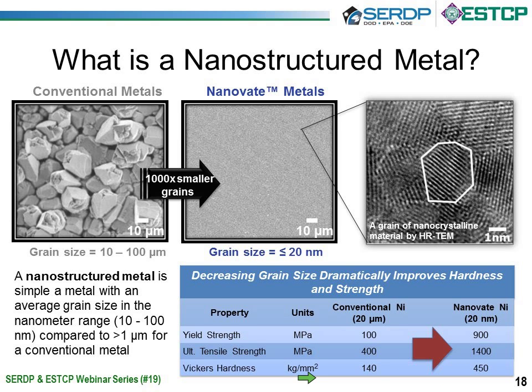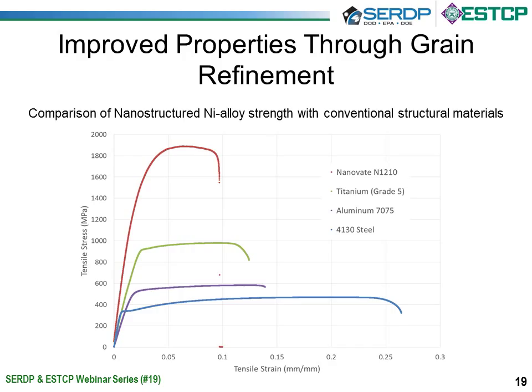On the next slide, it shows an example of the stress-strain curves for a nickel alloy compared to some conventional materials such as titanium, aluminum, and steel. So by decreasing the grain size, you can see that the nanostructure material has much higher ultimate tensile strength, but still has quite a lot of ductility or toughness. So it can be used for structural materials, for structural applications.